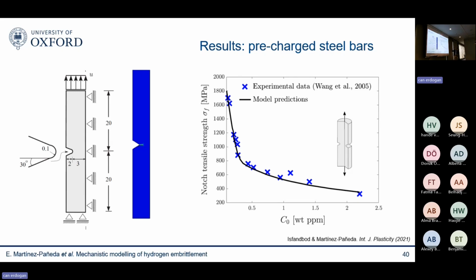So first, I'm going to show some results here. These are some representative comparisons with experiments. These are pre-charged steel bars. I think it's duplex stainless steel. No, these are high-strength steels. And you can see that they measure the notch strength versus the hydrogen content. Again, the symbols are the experiments, and you can see that the phase-field model seems to deliver a good agreement across a very wide range of hydrogen concentrations.